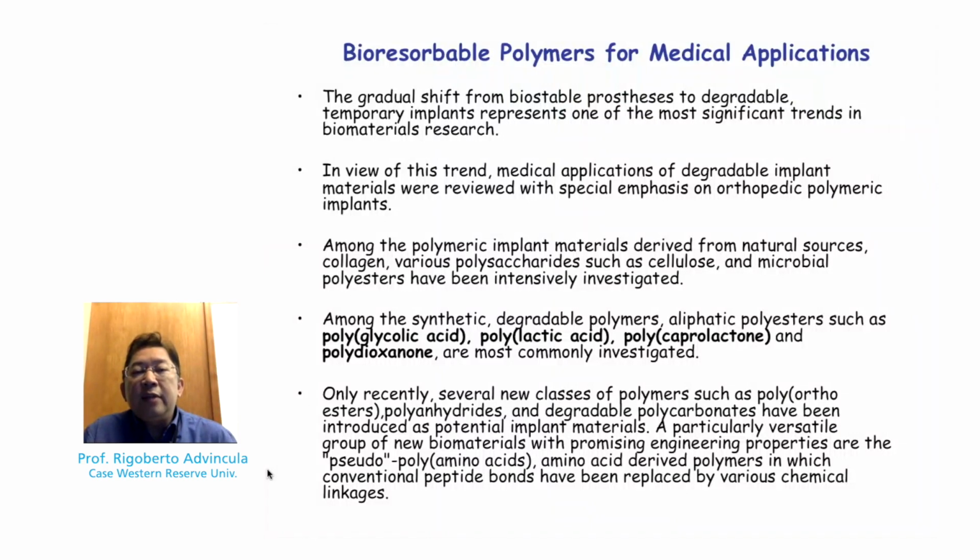So typical biodegradable systems can be in the form of polylactic acid, PLA, polyglycolic acid, polydioxanone, polycaprolactone, other types of polyesters, and so on. They are expected to initially have the shape of the tissue or implant, and then over time they're expected to degrade and go away safely as a biomaterial.